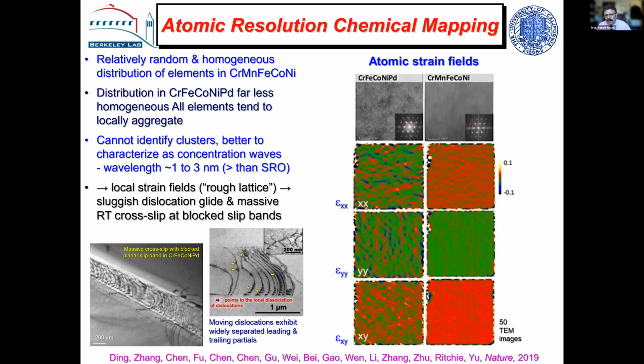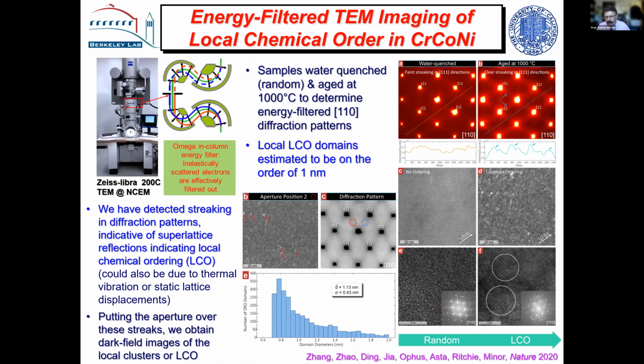A second approach was done to look at the more common form of local ordering, which is the nearest neighbors. This was done at Berkeley with Andy Minor again, looking at an energy filtered TEM, where you basically have an inline filter which gets rid of the inelastic scattered electrons. You get a cleaner image. And we looked at 2 conditions, one where we quenched it from a high temperature, and that was presumed to basically have a random structure, and then we aged it at 1,000 degrees to generate short range order. Now that's easy to say, but there's a big tail behind that about whether there's order there or not.